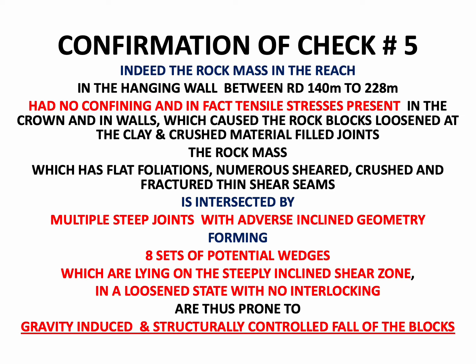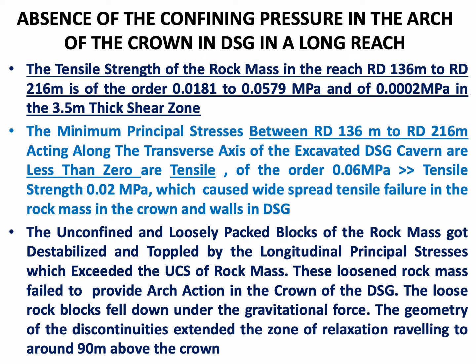The rock mass, which has flat foliations, numerous sheared, crushed and fractured thin shear seams, is intersected by multiple steep joints with adverse inclined geometry, forming 8 sets of potential wedges which are lying on the steeply inclined shear zone in a loosened state with no interlocking, are thus prone to gravity-induced and structurally controlled fall of the blocks. So absence of confining pressure in the reach of the crown in the DSG was there in the long reach. The tensile strength of rock mass in the reach 136 to 216 meters is of the order of 0.0181 to 0.0579 MPa.